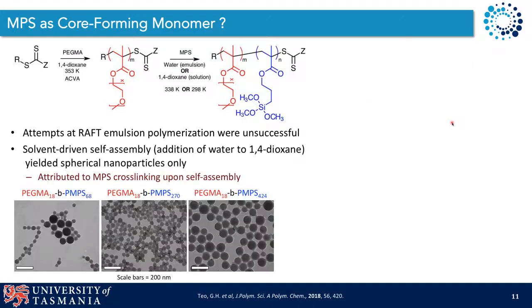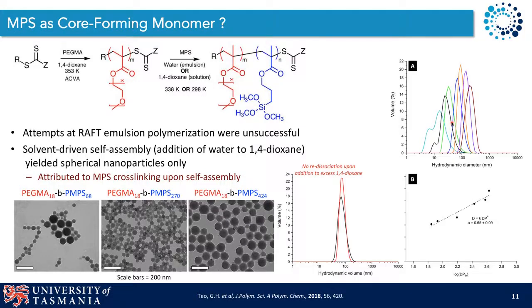And so we had to return to a solvent-driven self-assembly method, preparing our block copolymers with a PEG stabilising group with MPS as the core forming block, and adding water, a non-solvent for the MPS block, to a solution of the polymer in dioxane. Again, this only yielded spherical nanoparticles, which was attributed to MPS cross-linking upon self-assembly. We could demonstrate this by trying to redissolve or disperse our polymers back into their unimer state, which was not successful, even in the absence of any base to cross-link the material.